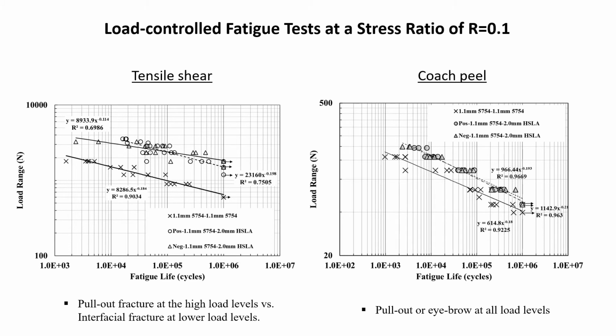Load-controlled fatigue tests were conducted for tensile shear and coach peel specimens, and the results show that the fatigue life is longer in the aluminum to HSLA steel spot welds than that of aluminum to itself. And all of the fatigue life data have a high fitting coefficient. After the fatigue fracture, we also observed the fracture modes. In tensile shear specimens, pull-out fracture was observed at the high load levels, and interfacial fracture was observed at lower load levels. In coach peel specimens, all of the fatigue fracture modes are pull-out or eyebrow at all load levels.